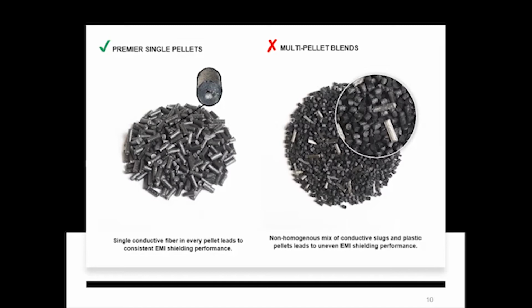So you'll hear those terms used quite often. And, you know, they'll get you some kind of decent results for the most part. But the problem with this type of blend is the fact that you can never guarantee a 100% perfect mix. There's always going to be some settling and some inconsistency of the conductive material to the non-conductive material. Exactly. So in the process of things like transporting the material, a lot of the times the metal slugs will actually vibrate and sink to the bottom of the packaging. And at that point, early shots might have a much higher metal composition than later parts.